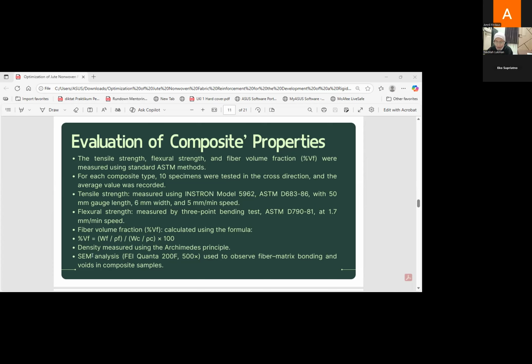And for density in this paper, they measure the density using the Archimedes principle. And the last is they use the SEM analysis to observe the fiber matrix bonding and voids in the composite sample.